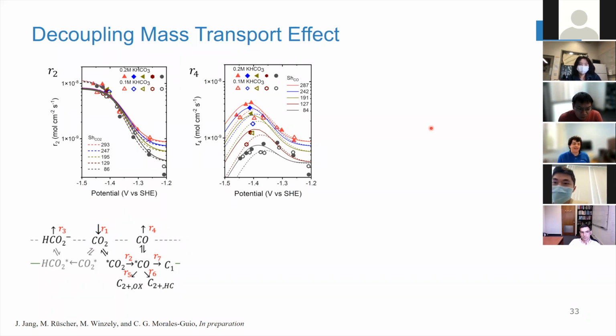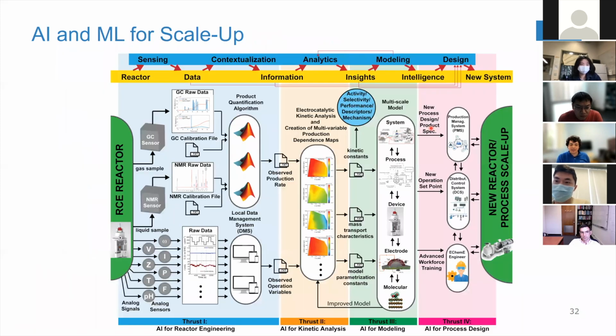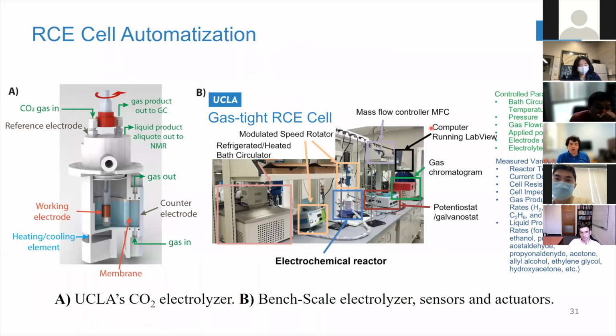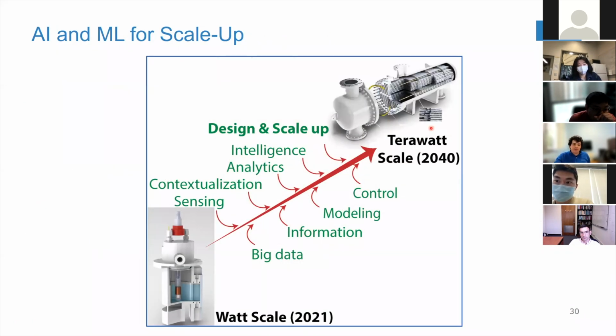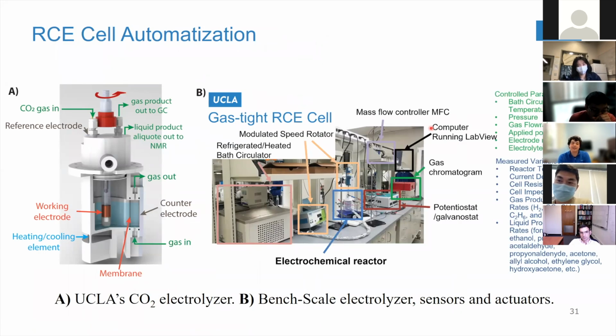Right. So yes, that's a very important aspect of our research right now. We train the system with data that is collected over 1 hour, 1 hour 20 minutes. But the control experiments that we run for 4 hours or so, and during those 4 hours you actually have a lot of degradation of the catalyst and changes in the selectivity. So what we're working on right now is a system that can retrain itself as time passes, so you can account for the degradation of that system. So effectively, when you're trying to drive the system from one set point to the next, it accounts for that degradation. Yeah, so that retraining is based on real data that we're collecting over time.